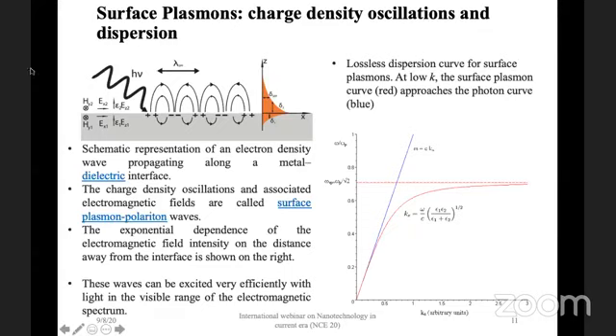When they come onto the surface, and somehow if there is a photon which hits the surface, it creates oscillation in the charge density. So it depletes electrons from one region, and then these accumulate at the other one. So it kind of forms an oscillation, which we call charge density oscillations. And they do oscillation in a synchronized motion, and when the energy is quantized, we call them surface plasmon modes of the metal. You can look at that in this figure, where this oscillation is shown by plus and minus signs, which show that the density of the electrons is increased and decreased.